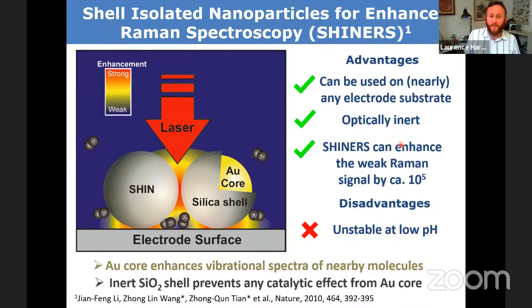It's optically inert, so these particles don't interfere with the Raman spectra, and we can get fairly usable signal enhancements up to 10 to the 5. And this is some of the challenges that we're working on, developing certain particles which have a much greater pH stability.